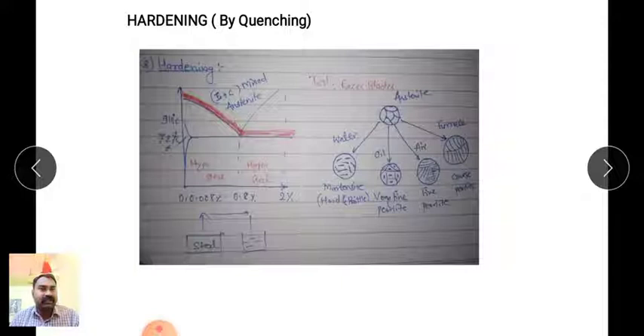Here a few more structures are shown. Whatever the austenite on which we perform the hardening heat treatment, by using different cooling media, different structures will be obtained. Here austenite is transformed to martensite by rapid quenching in water. And its property is hard and brittle. Martensite is the toughest and hardest structure out of the other structures. Suppose we are using oil as the cooling medium for austenite. In that case, a very fine pearlite structure will be observed. If austenite is cooled in air we get fine pearlite, and if austenite is cooled in the furnace we get coarse pearlite. So depending upon the different cooling, we can observe here martensite, very fine pearlite and coarse pearlite.